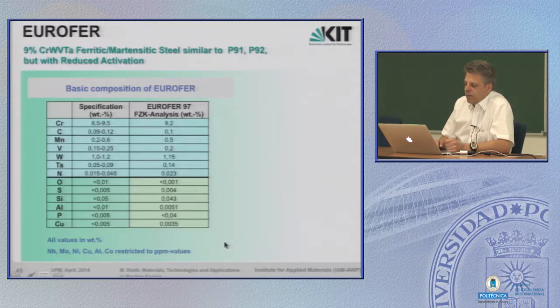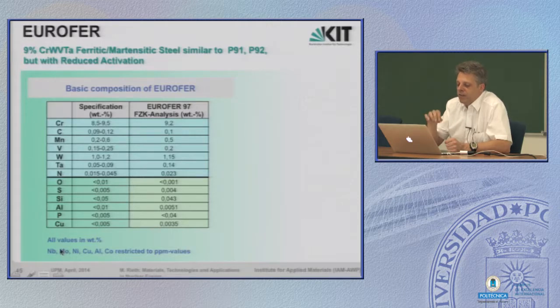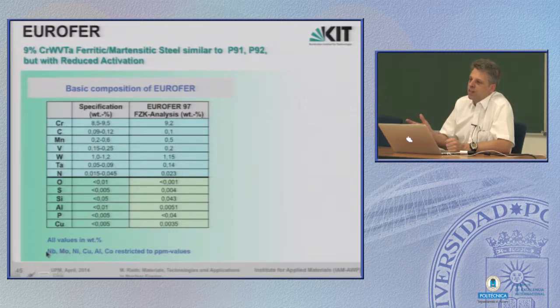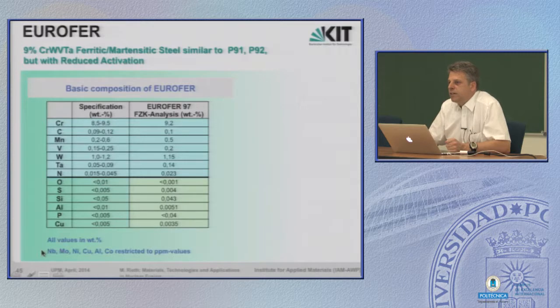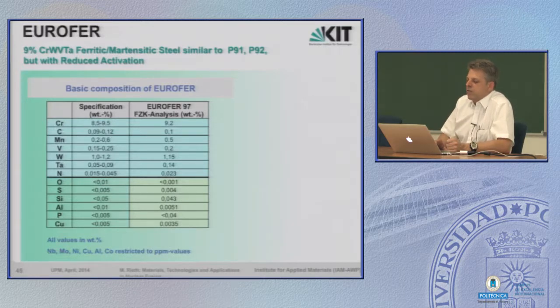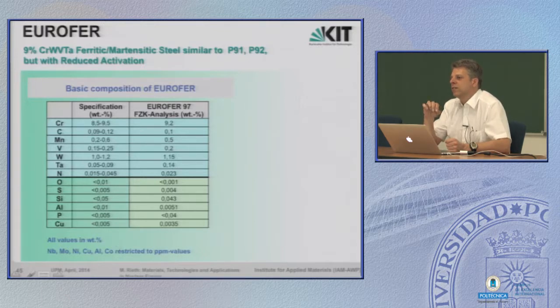Where we have to be especially careful to avoid elements, this is for niobium, molybdenum, and aluminum. These produce very long-living isotopes, even in the ppm range, which means parts per million range of these elements. It would destroy the low activation capability of Eurofer. Then there is nickel, which we also want to avoid due to helium formation, and copper as well. Cobalt, and to a certain degree also tantalum, contributes to short-term activation. That's another issue when it comes to radioactivity.